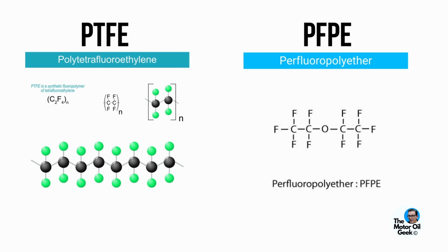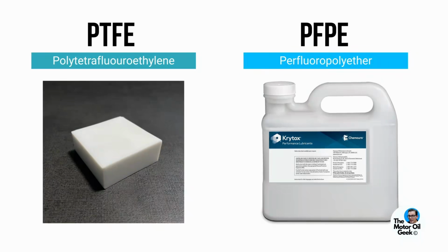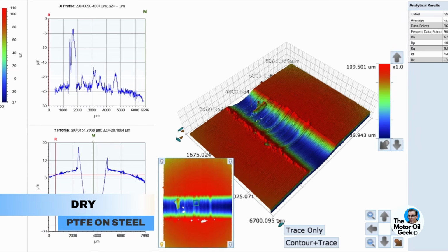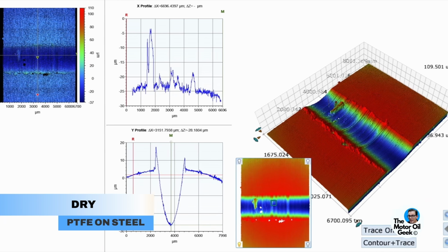where it's at. And going right back to the beginning when we talked about space, you don't need the lubricant, the DLC works. Right, and because most lubricants will not exist in a vacuum. Well, they'll just disappear. Unless it's PFPEs, and that brings up a good point. PFPE lubricants won't evaporate in a vacuum, and that fluorine in there also has a cousin, PTFE. Yes, it does, PTFE, good point. So we ran those PTFE tests, the block on ring and the other. And again, PTFE, super low friction as long as it's there. As long as it's there, which in the block on ring test we saw disappear.